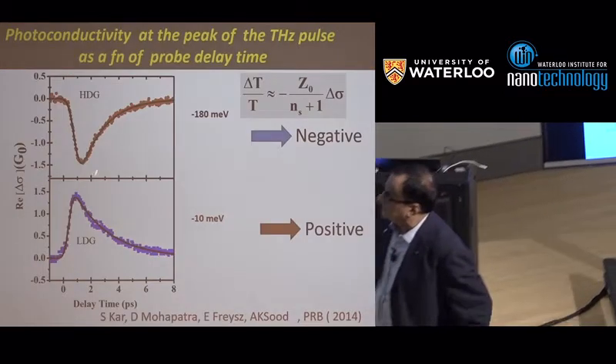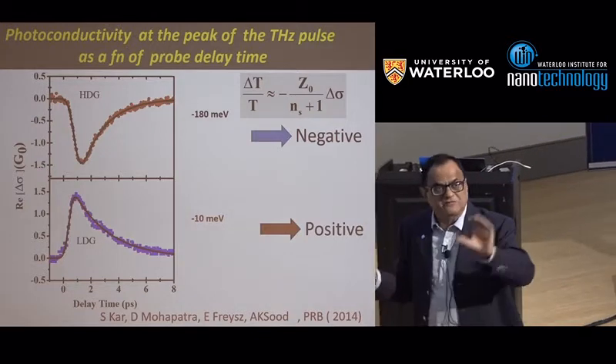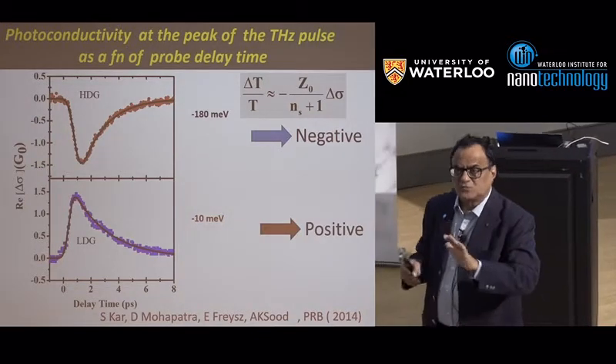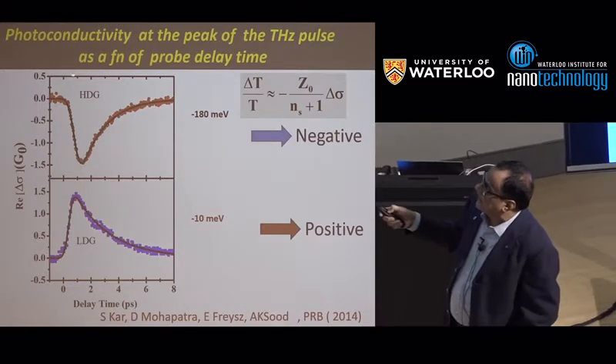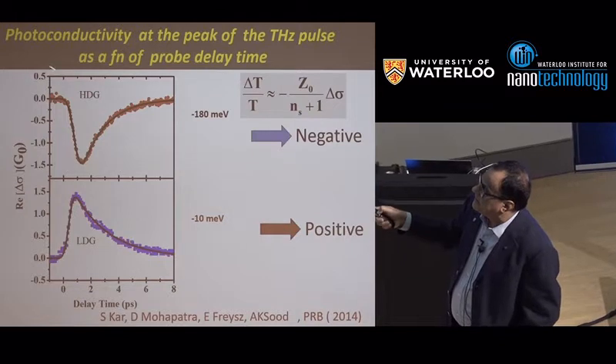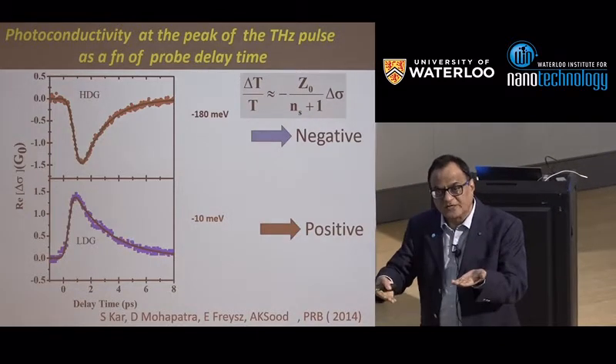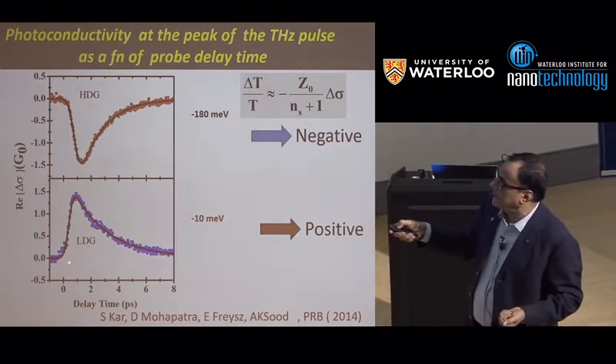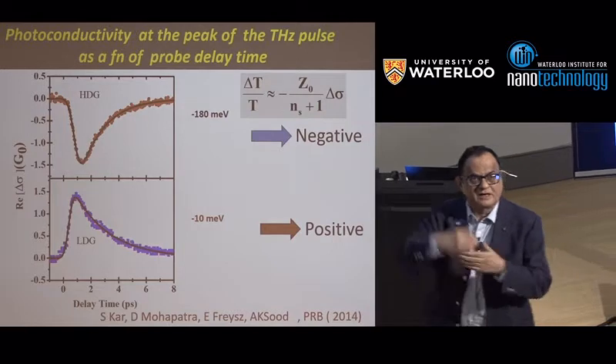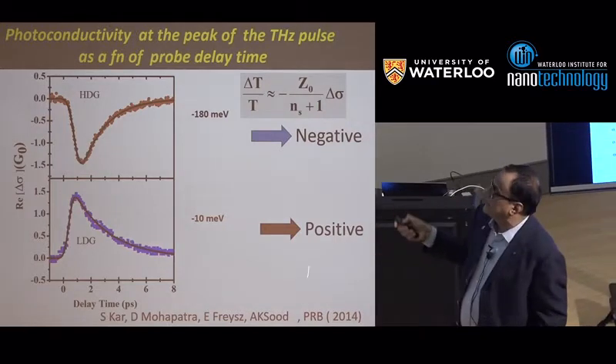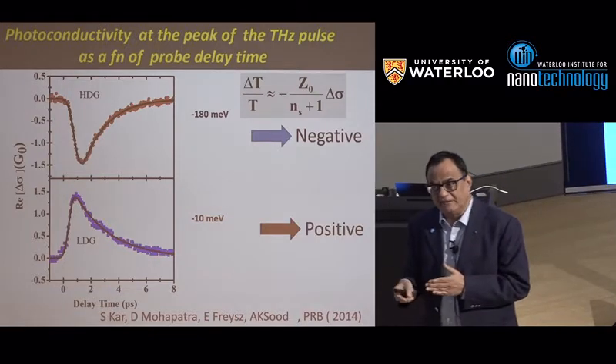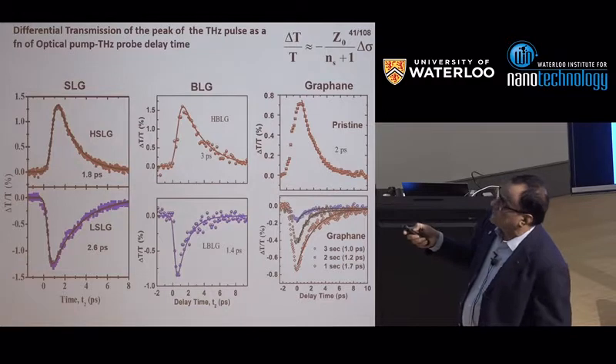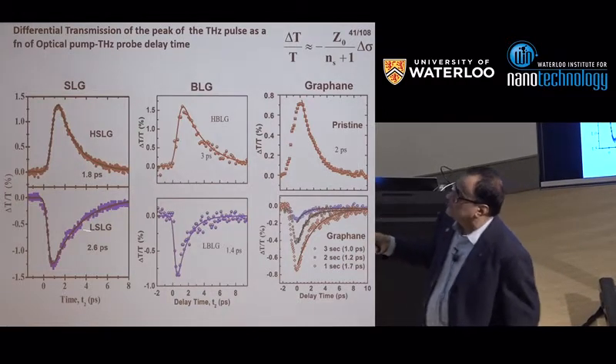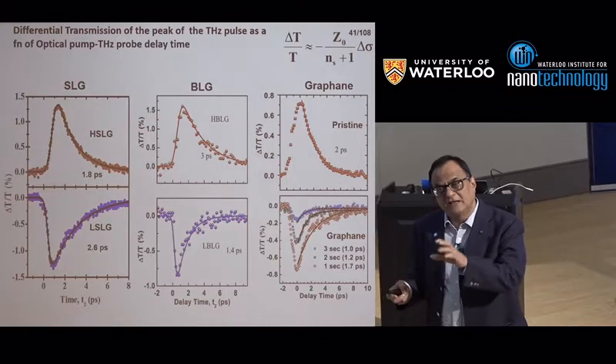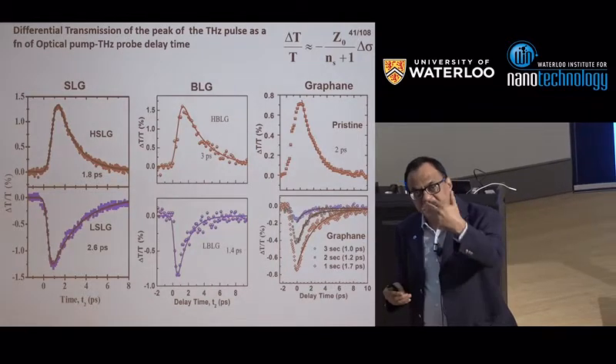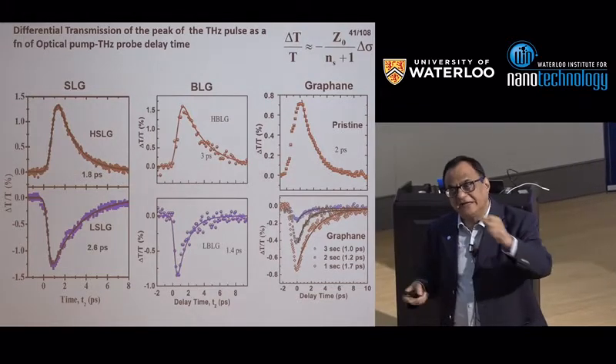But the surprise was that when you measure different types of graphene, you get different results. This was the case in the literature: for highly doped graphene, the conductivity decreases on optical pumping, which is counterintuitive. But on low doped graphene, it behaves as you expect in a semiconductor, the conductivity increases. So this negative and positive, we wanted to understand quantitatively. How do we understand this? We did various types of graphene, and a similar conclusion is valid: for low doped graphene, conductivity increases on pumping, but for highly doped graphene, it decreases.